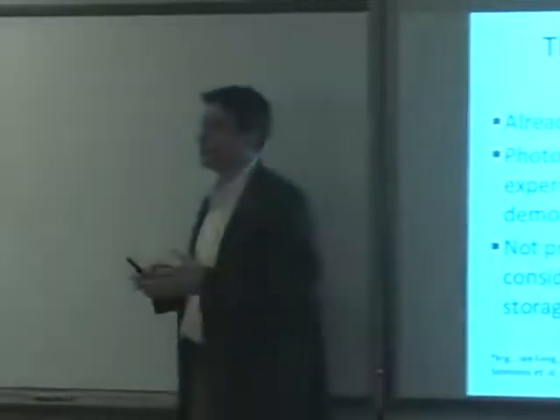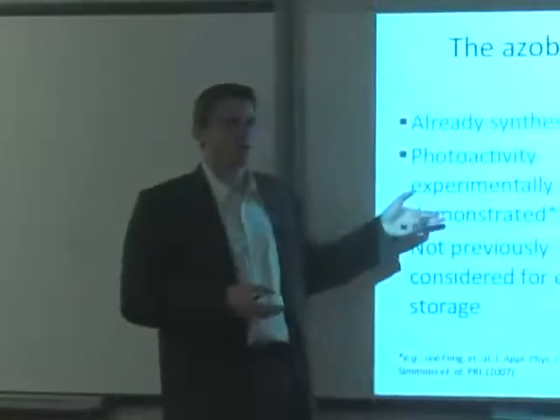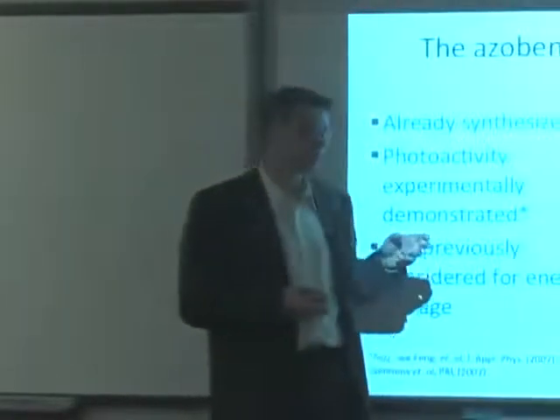Okay, now let me tell you that a photo switch by itself is a really terrible solar thermal fuel. Azobenzene stores just 0.6 electron volts per molecule, so its energy density is not very high, and it has a lifetime of about an hour. That's why we wanted to see if we can tune those two parameters, and that's what the template allows us to do. So let me walk you through what the role of this template is.